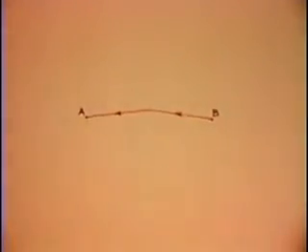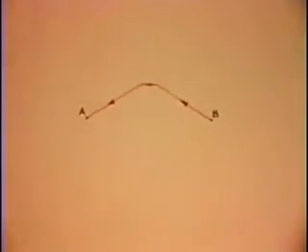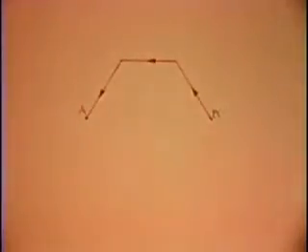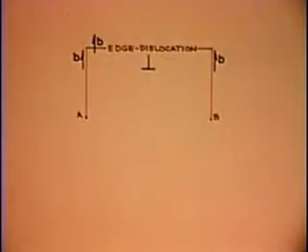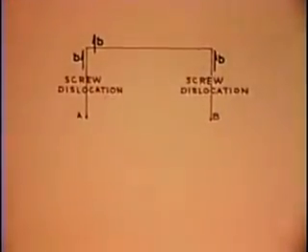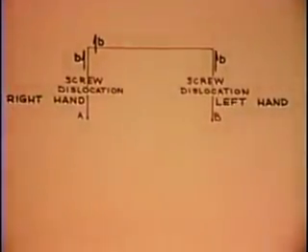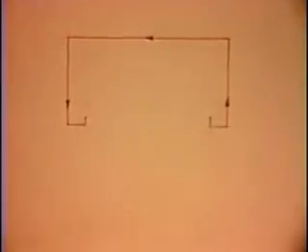The Frank-Read source is here illustrated as composed of straight edge and screw segments. The segments normal to the loop's Burger's vector are edge, and those parallel are screw. Parallel segments on opposite sides of the loop point in opposite directions, and hence are opposite dislocations.